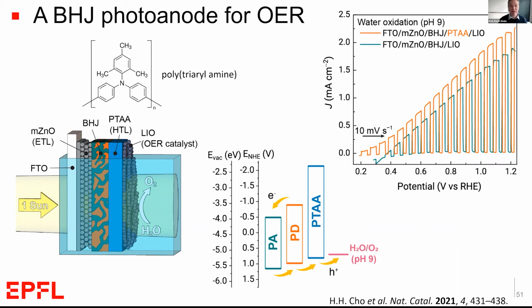But in fact, this is one interesting approach to think about: making a bilayer on that length scale of 20 nanometers of donor and 20 nanometers of acceptor, and then thinking about how to make a sheet of this. Maybe we could have a photocatalytic sheet that would work fine. As long as we have the materials in close enough proximity so we can get light absorption and the exciton can diffuse to the interface between the donor and acceptor in the organics, then we don't need the bulk heterojunction. We just need some sort of heterojunction.